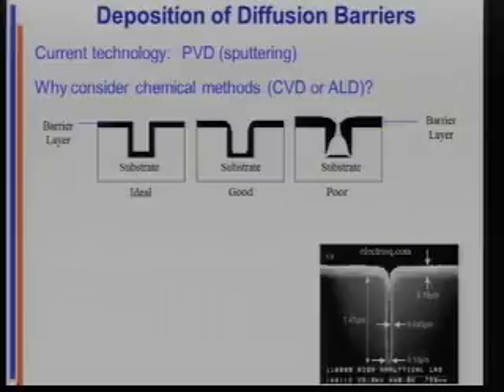Now, if you think about putting your material down with a chemical reaction, synthesizing it in place, as it were, then you don't have this problem, because the reaction kinetics for materials deposition are the same on the top as they are on the sidewall as they are on the bottom. And so you can get a much better approximation of perfection. So this is a profile of material deposited by what's called chemical vapor deposition. And so then when you fill this feature with copper, with the problem here, we've got pinch off, we have a void, we have stuff leaking out the bottom, and then this is a much better solution to the problem.